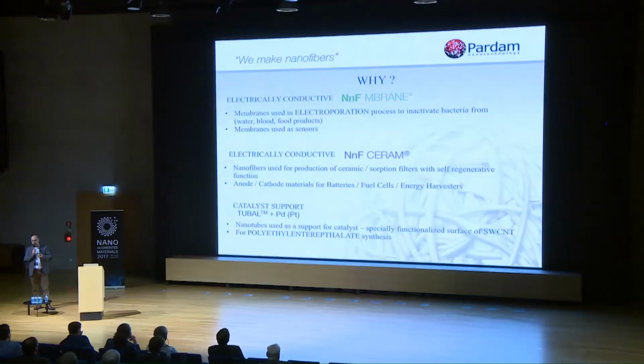The electroporation is a process of inactivation of bacteria by electric field during the filtration. Today, if you want to remove bacteria from water, you have to use either chemicals or very fine filters. Very often, you filter out a lot of good stuff from mineral water, for example, in order to remove the bacteria, to get the sterility. So, with nanofiber electrically conductive membrane, we have studies and first results from the electroporation process that we can remove up to 99.97% of bacteria by adding electric field to the membrane during the filtration, which is quite amazing.